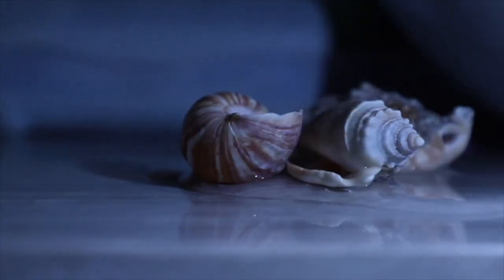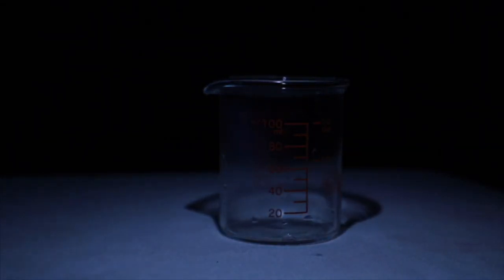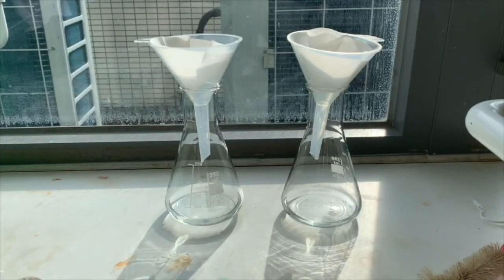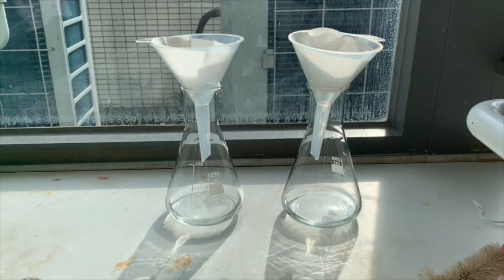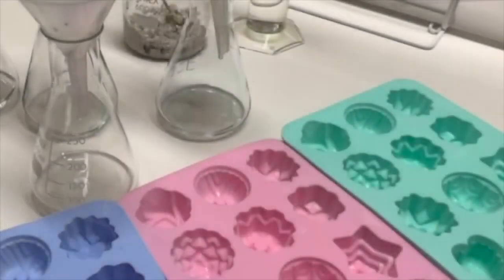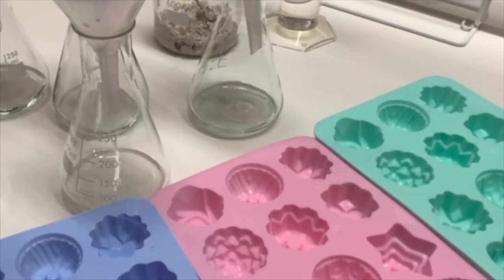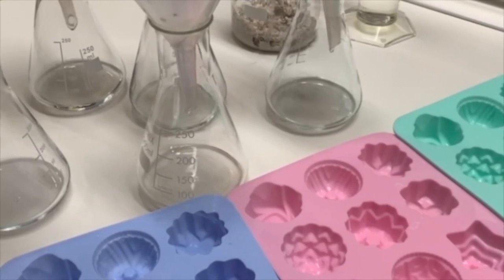In terms of the methodology and procedures, we first acquire clamshells from the dining table and place them in an autoclave to remove germs. They are then ground in a blender and separated into beakers. To extract chitin, two processes are conducted: chemical demineralization using 0.5 molar hydrochloric acid and chemical deproteinization using 0.5 molar sodium hydroxide.